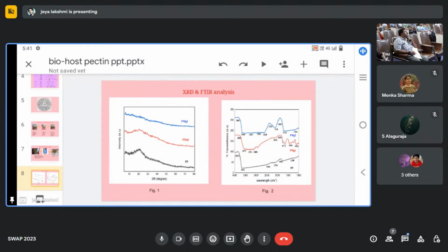I first take the XRD and FTIR analysis. For XRD, I have taken 3 samples. One is pure pectin, and the other 2 are 30% magnesium chloride with pectin, and 40% magnesium chloride with pectin. For pure pectin, we have a peak in the range of 20 degrees, and in the next sample we have a peak, but its intensity is slightly low, and in the next sample there is no intensity, which reveals the complete dissolution of the salt in the polymer. It also indicates that increasing the salt concentration increases the broadening of the peak and decreases the intensity of the peak.